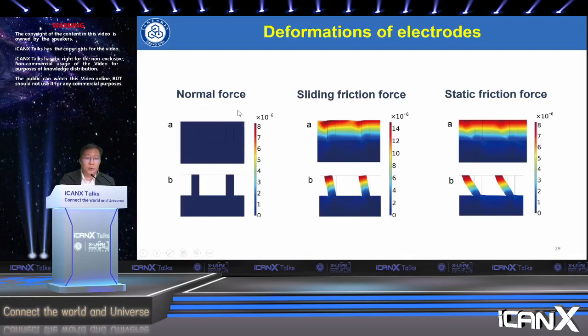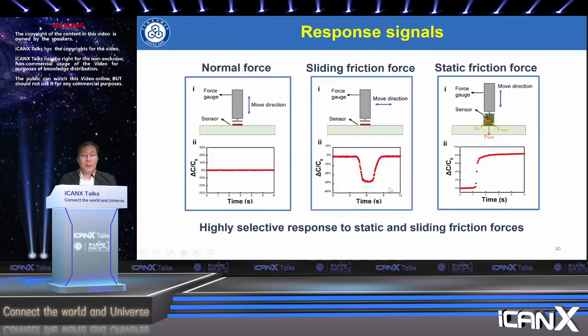And we did the finite element simulation analysis. Due to the lower Young's modulus of the Ecoflex compared to that of the PDMS, the microcolumn electrode can be easily deformed under the shear force. When only the normal force is applied, no obvious deformation of the electrode was observed. But under the sliding friction force, the electrode was laterally bent but not stretched. Conversely, when the static friction force was applied, there's no relative displacement at the contact surface, and the electrode was laterally stretched. And then we did the experiment to verify this result. Here you can see that, with this apparatus, the figure shows a real-time response curve under the normal force, static friction and the sliding force. And these results agree well with our simulation result.